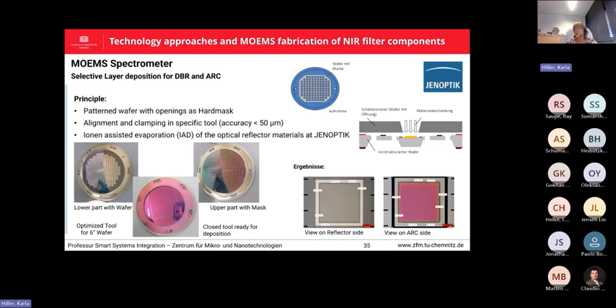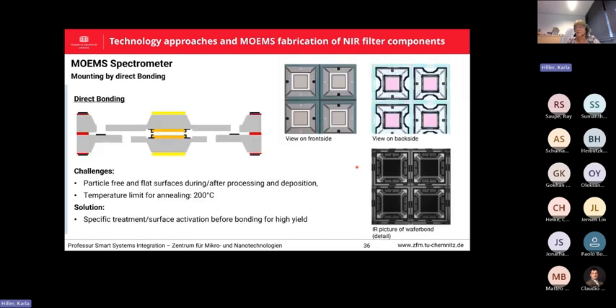And this tool we send directly to this company. They do the deposition process, and then we demount everything. And here we see some results. This is the view on the reflector side, and this is the view on the anti-reflective coating side. The area here is 2 by 2 millimeter, so it's not so critical from the alignment point. And this gives us a large flexibility to change the wavelength range by adjusting the materials accordingly.